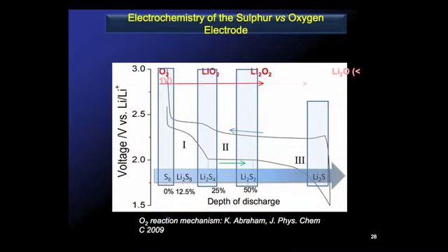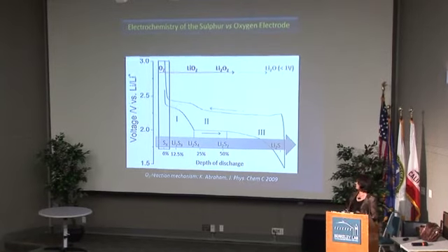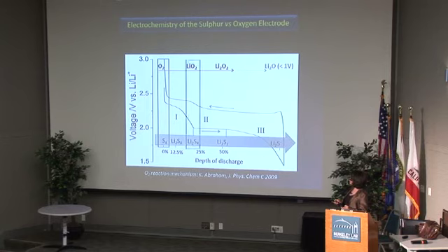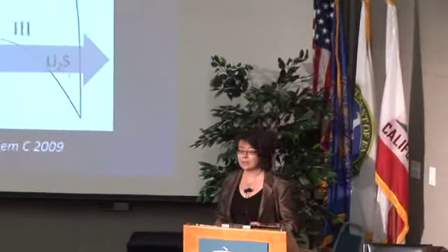If we compare the reaction chemistry for these two systems, they're actually rather similar. This shows the voltage profile for the lithium-sulfur cell and the reactions that occur, and this shows the reactions for the lithium-air cell. In both cases, we have elemental oxygen or sulfur starting off the process. We reduce the material to form ultimately this soluble polysulfide, or in this case, this highly unstable reactive intermediate, lithium superoxide. In the case of the sulfur cell, there's a cascade or sequence of polysulfides that are soluble species, and at this point the system becomes insoluble as you move through this part of the regime. Comparing things, finally at Li2S2 we have an insoluble product, as we do in the case of the peroxide. The oxygen mechanism has been elucidated by Abraham at Boston.